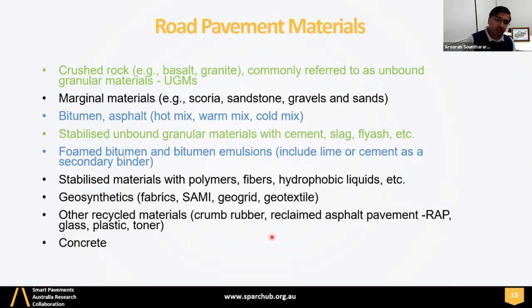And geogrid is also commonly used on soft soil or soft subgrade to strengthen the subgrade before we place the UGM, right? So if the subgrade is too soft, what would happen is you will require a larger or thicker pavement, which may not be cost effective. So what they normally do is they strengthen the subgrade, which can be by cement stabilizing or lime stabilizing the subgrade, or placing the geogrid so that the subgrade will receive enough strength.